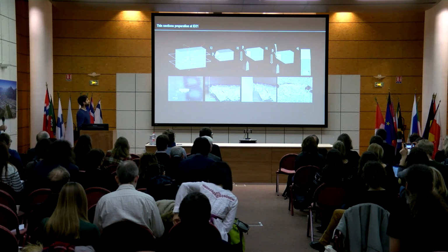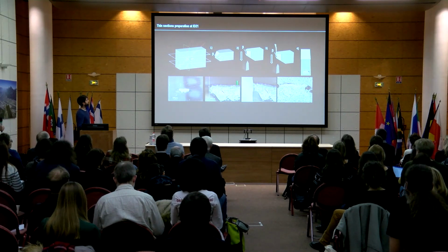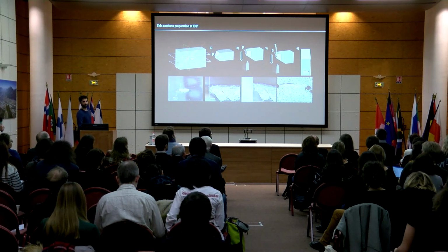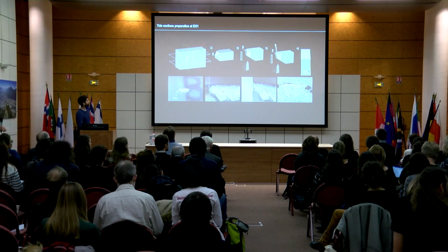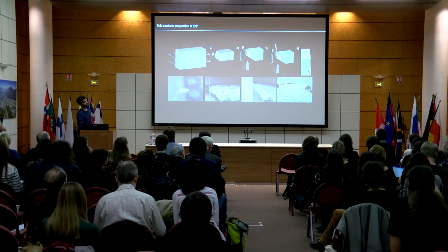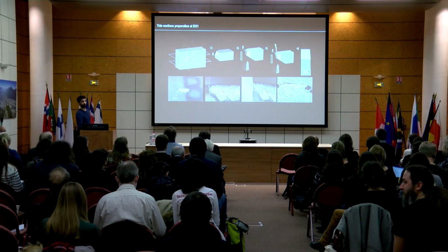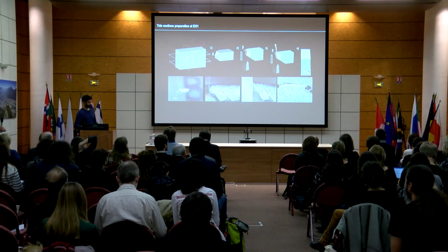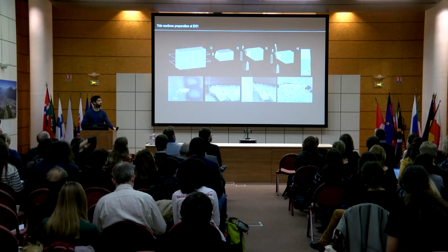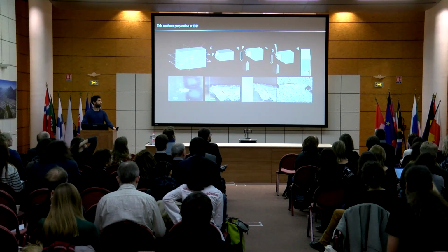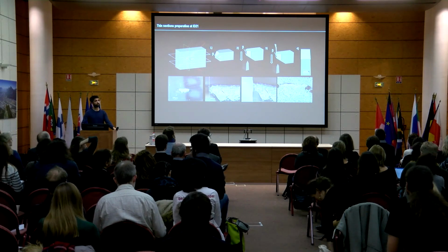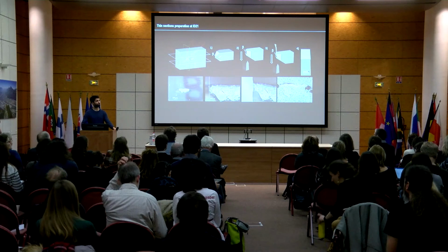And instead of cutting parallel to the surface of the sample, what you see here is that we decided to cut perpendicular to one side of the section. So even if you have samples which have been taken decades ago, embedded decades ago, and you consider that thin sections may be better than cross sections, it is something we can do a posteriori. What I like in making thin sections is that you have a very good control of the volume which is analyzed. In particular, when you do mapping in transmission with micro X-ray diffraction, you know exactly the volume which is probed, and you have a good chance that the composition is homogeneous in the beam direction. So this is my advice.